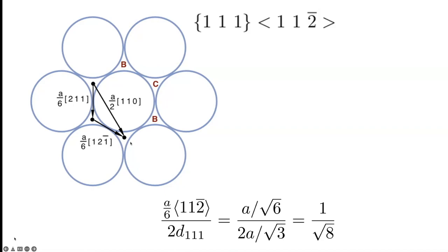Okay, that's a lattice vector. So if we translate one layer over the other by that vector, nothing changes. But this displacement here is not a lattice vector. It takes you from a C position to a B position. So if I move along here, then I'm actually changing the stacking sequence. And this is known as a partial displacement because it doesn't restore the symmetry of the stacking sequence. Okay. So some of you might know that this is a Burgers vector, which is a Shockley partial dislocation.